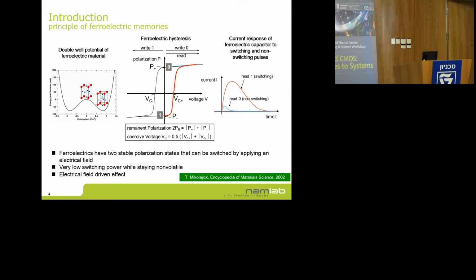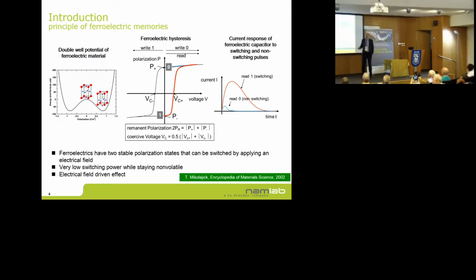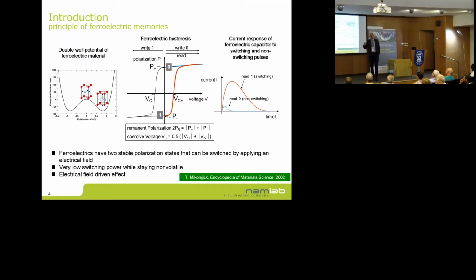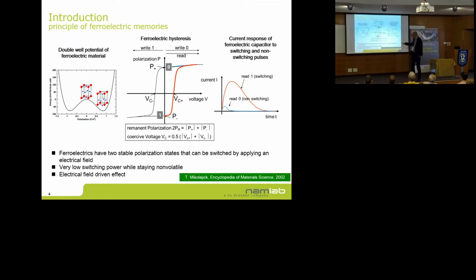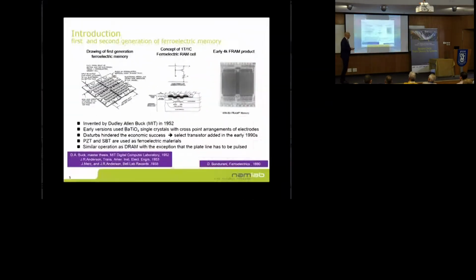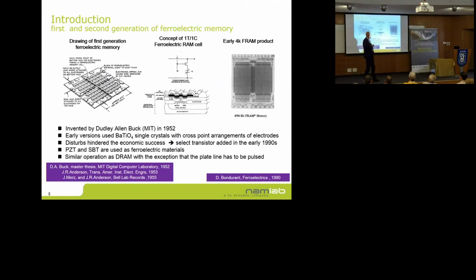So I would like to start with explaining why ferroelectrics are so good for non-volatile memories. The reason is basically, in a ferroelectric, because of the crystal structure, you have two stable polarization states that are separated by a barrier, which is good to make it non-volatile. At the same time, the switching between these two states can be done strictly by an electrical field. So we don't have the inefficiencies that we normally have with all the other emerging memories in the switching process. And that's why ferroelectrics have been studied for a long time for non-volatile memories.